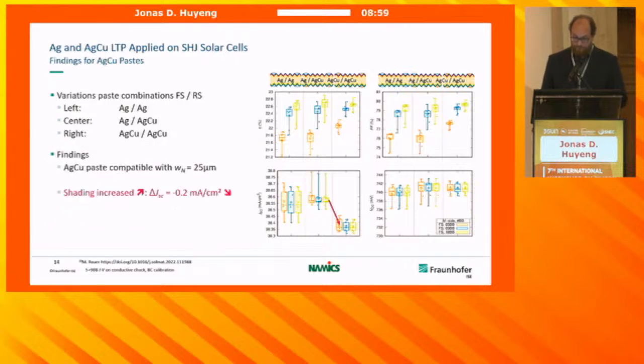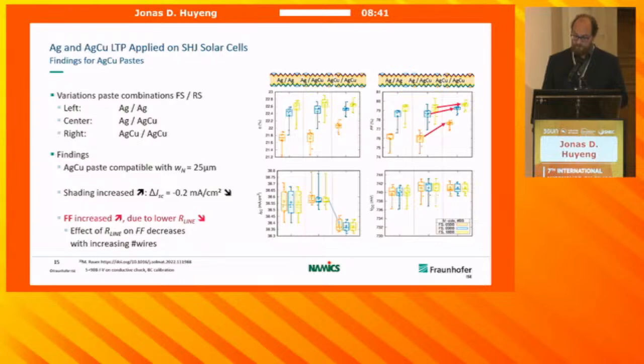So what are the core findings here? We can see that there's a prominent drop in the JSC when we put the silver copper paste to the front side, because we have wider spreading of these pastes due to the printing, even if we're using the same screens. So they're not fully optimized, as I already said. Also, there's a higher laydown, so you can also see that the fill factor is increased because the line resistance for these fingers is lower. Of course, when you increase the number of busbars on your cell, this effect is less important.